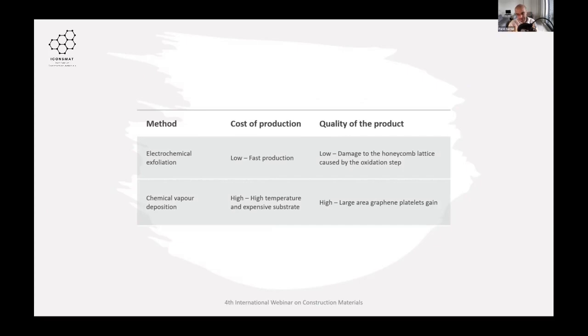Electrochemical exfoliation, the option that we've chosen, refers to the process during which the graphite sheets are oxidized in an electrolyte followed by ultrasonication. Hydrobromic, hydrochloric, and nitric acids plus sulfuric acid are typically used as electrolytes, from which sulfuric acid is proven to perform at the highest efficiency amongst the other acids. So we used sulfuric acid for that reason in our studies.